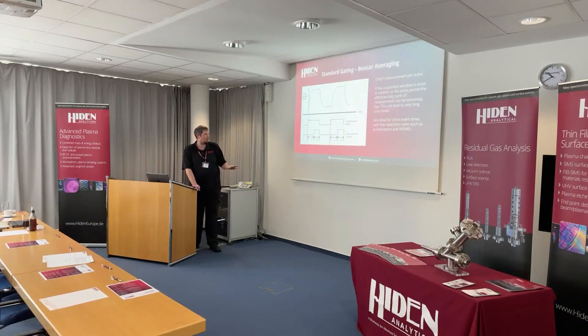It works really well, but it does have a weakness in that the narrower you make the acquisition window, the lower the effective duty cycle of the measurement is. So the instrument ends up scanning for a much shorter time, and it's just waiting for much longer.